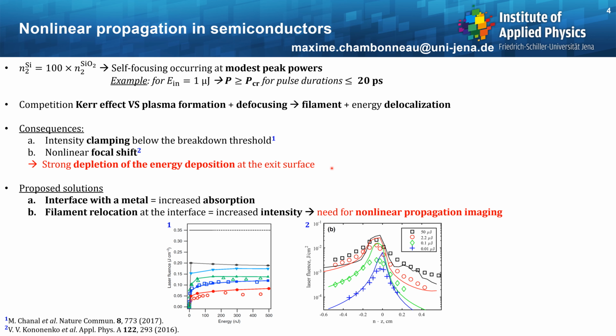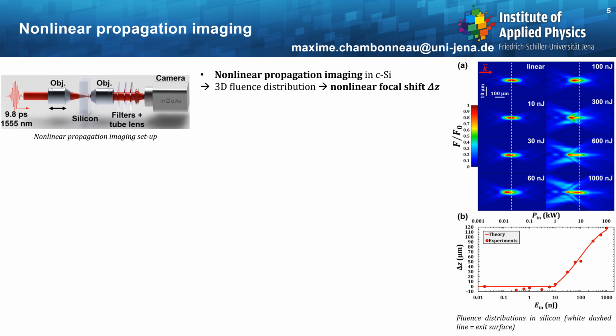So here are the solutions we propose. First, in the frame of laser welding, we will deal with an interface with a metal, meaning that there is increased absorption, which is kind of good. And second, we will relocate filaments at the interface in order to maximize the intensity at the interface. But to do so, we need nonlinear propagation imaging. And this is exactly what we did.